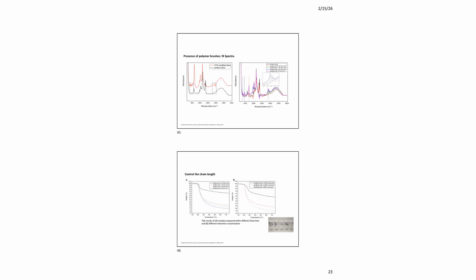To create a block copolymer, a solution of the first monomer, PEGMEMA, is flowed through for 1 hour, followed by a solution of the second monomer, NIPAM, for another hour. The presence of these polymer brushes is confirmed by IR spectroscopy. Spectra show the appearance of characteristic polymer peaks after the grafting reaction.